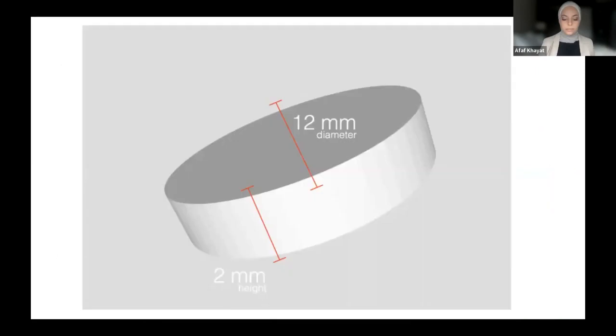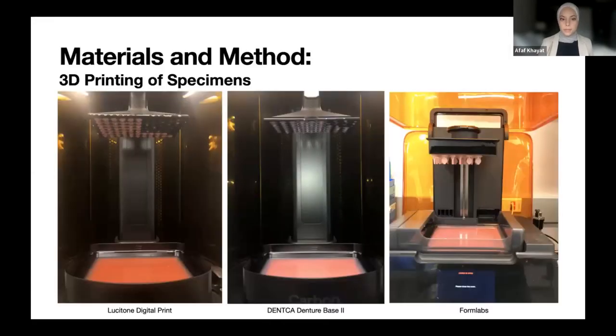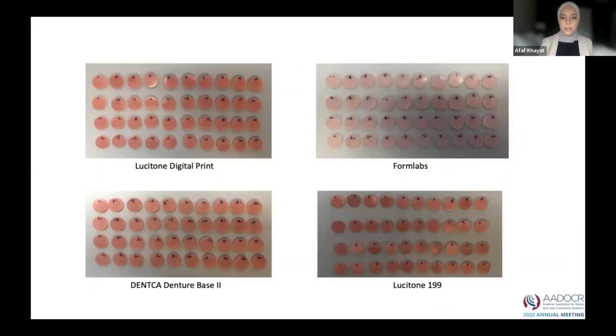A total of 216 specimens, consisting of 54 specimens of each type of denture resin, were prepared as discs measuring 12 millimeters in diameter and 2 millimeters in thickness. This was the finished printing job of the specimens. These are the final specimens after polishing and labeling.